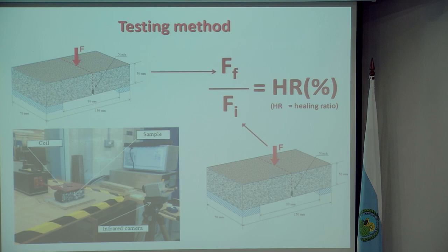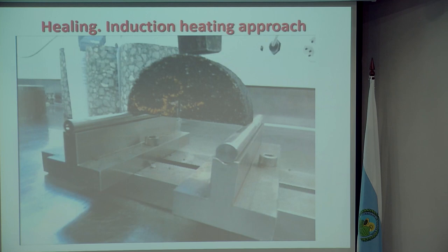It does vary. The test also can vary. We could also use a very simple geometry, such as the semicircular bending test. So the semicircular specimens, very easy to manufacture. Could be a core from a road, or it could be a sample made in the gyratory compactor. Cut it in half, notch it, do the test, damage the specimen in terms of fracture, put it under induction heating, and obviously re-heal it and retest it.